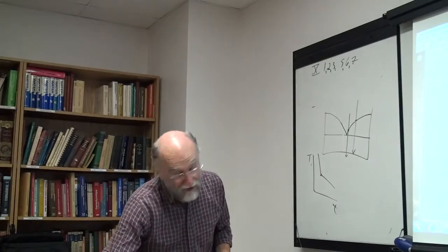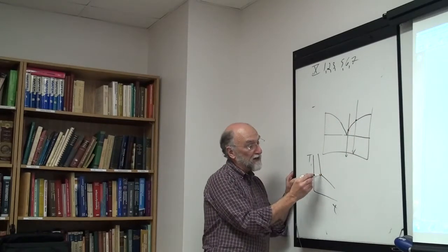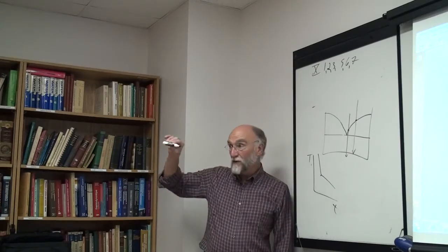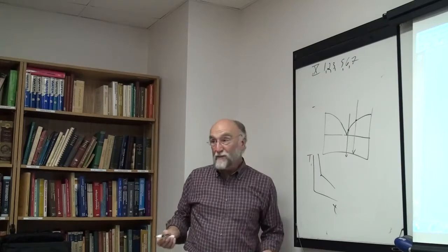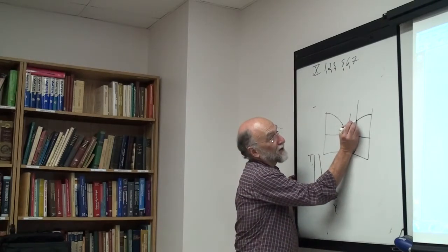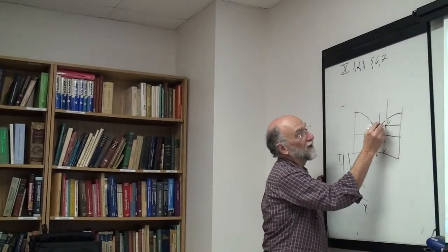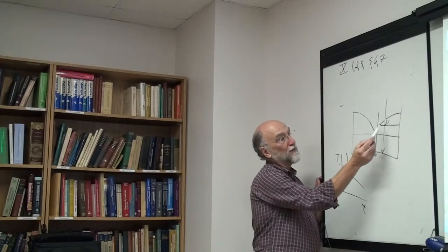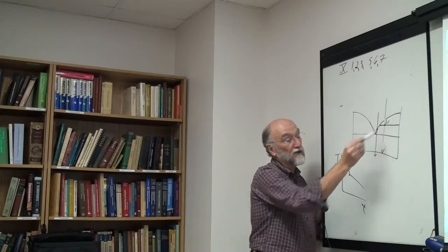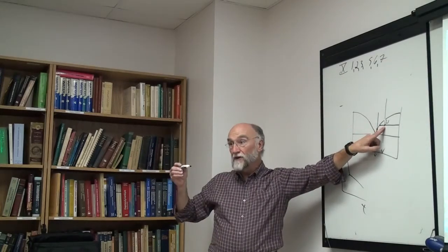The reason being, you just think of the lever rule. It starts here. Remember, what you're really seeing is the heat effect. The heat is being given off, and that slows down the cooling. So you need enough heat to be given off in order to see something. Now if you're up here, the liquid starts here, supposing you cool it 5 degrees. After cooling 5 degrees, by the lever rule, the amount of solid to the liquid is this distance over this distance. In other words, quite a bit of solid has already precipitated during a 5-degree drop.